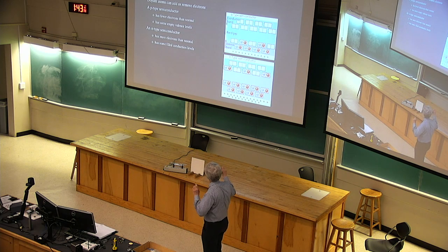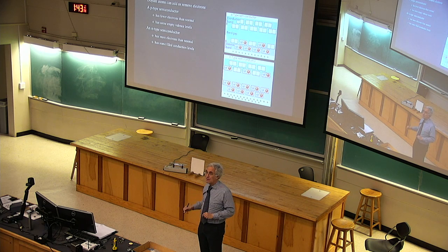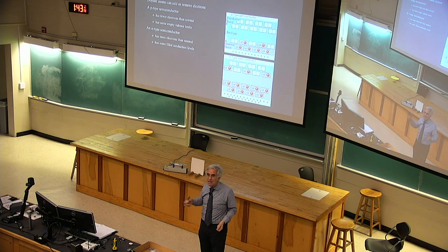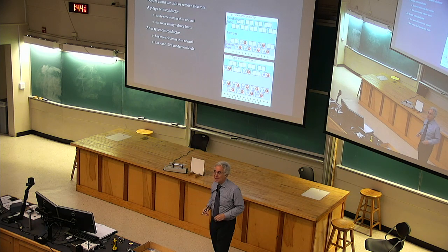When you put extra electrons up there in the conduction level and you apply an electric field, those little negatively charged electrons move. So what's moving through the material is truly a negatively charged thingy. Okay? So the current is traveling through this material by way of these negative charges moving along. So we'll call it N-type material because it's negative type things carrying the charge, carrying the current.